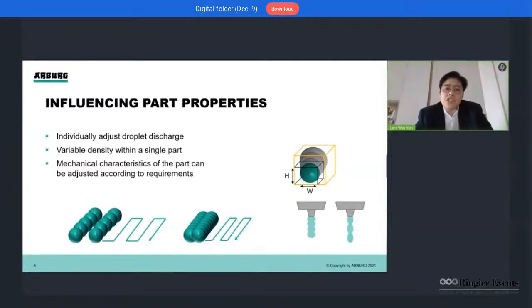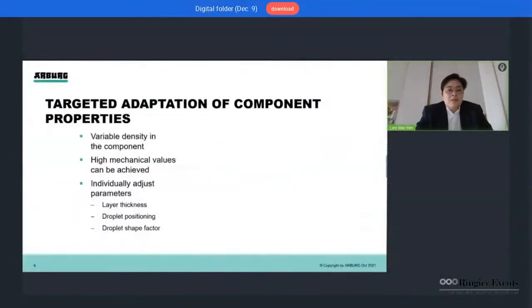In order to obtain the best part quality, we need to take into account the different material properties, especially viscosity and temperatures. This will lead to varying shape and size of the droplet, as displayed in the bottom right corner here. As you can see, these droplets are a little bit shorter and these are a little bit longer. These result from different viscosity and temperatures. The data processing software allows the user to adapt the different parameters of new materials that need to be qualified. The same applies to the ability to vary the density of the part, as you can see here.